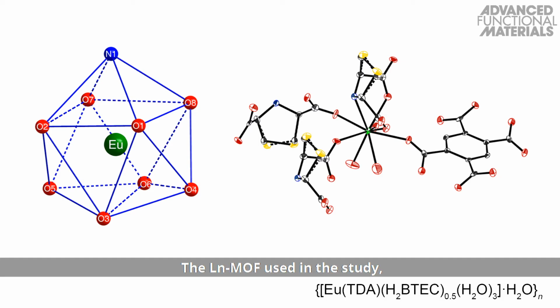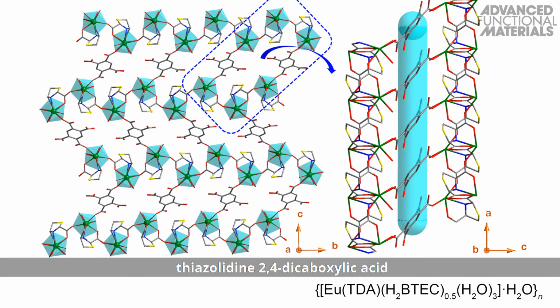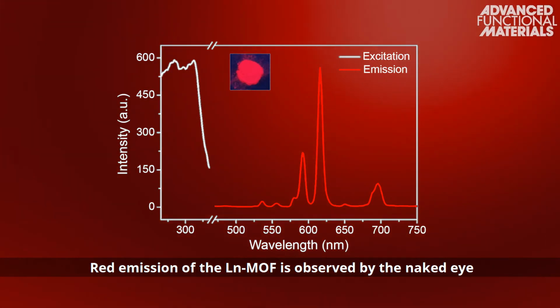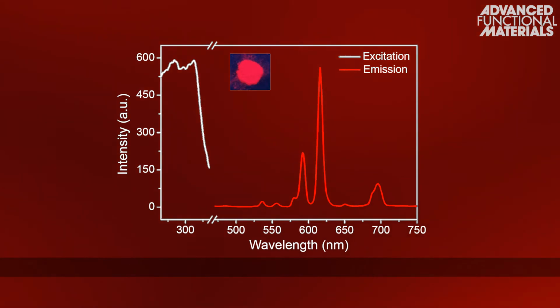The lanthanide metal organic framework used in the study is composed of europium 3 plus ions coordinated to sensitizers of europium 3 plus luminescence, thiazolidine-2,4-dicarboxylic acid, and 1,2,4,5-benzene tetracarboxylic acid anions. Red emission of the lanthanide metal organic framework is observed by the naked eye under 254 nanometer irradiation.